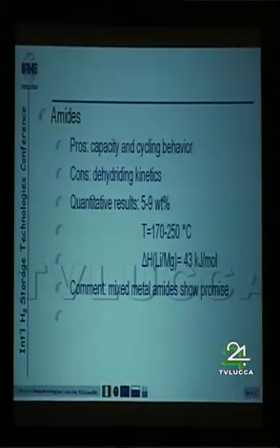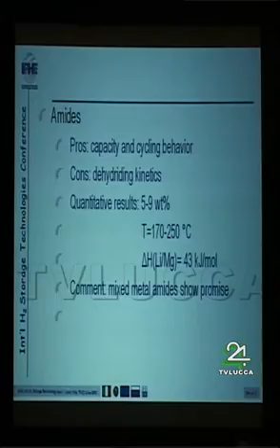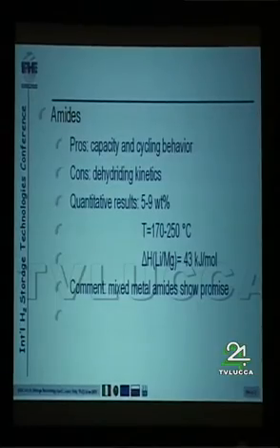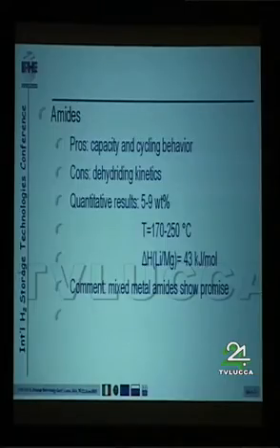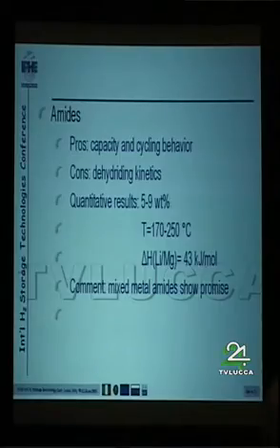Amides. The pros is capacity and cycling behavior. Cons: dehydriding kinetics. Quantitative results are promising, from 5 to 9 weight percent. Temperatures are still a little bit high. We included between 170 and 250 degrees centigrade. Enthalpies 43 kilojoule per mole. Mixed metal amides show promise.